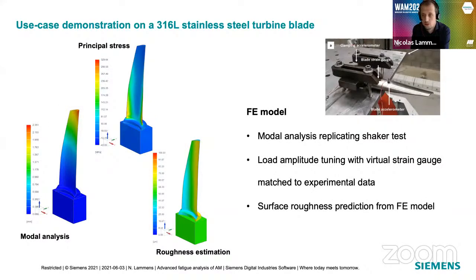So then we looked at the component itself. You see it on this picture here. And this component was tested experimentally in a shaker setup. So this is the part of the shaker. And there's also a strain gauge applied here to the blade itself to be able to know how much strain and stress is applied during the test. We replicated that with an FE model. So we did modal analysis where we tuned the load so that we would get the same strains as the strain gauge measured on the component. And then we did a predictive analysis where we looked at principal stresses, the roughness, and also the orientation of each individual element relative to the build chamber orientation.